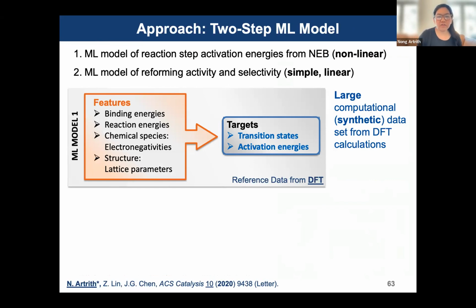So we decided to have a two-step approach with two types of machine learning models, because we know that we can do the DFT calculations with large NEB data to get the activation energy. So we apply nonlinear models. And then the second one: how can we understand and predict the reforming activity and selectivities? Because we have to find the relationship with the experimental measurement. It's only 7 data points. So I decided to use linear models, like you can see here. This is the physical properties that we collect in the data, and this is the target of the prediction that we want to have.